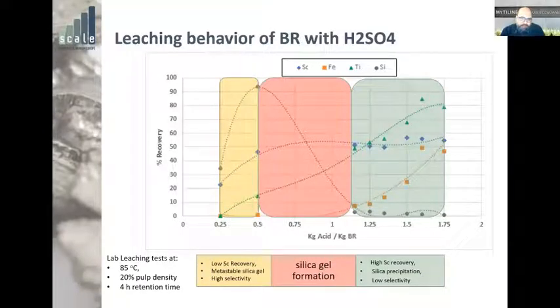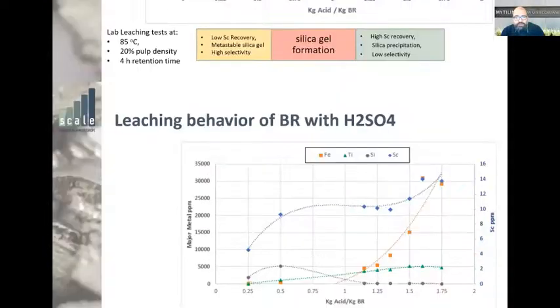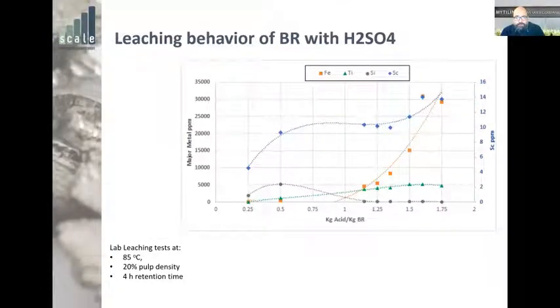And then there is this very narrow region in the beginning where we get relatively low scandium recovery. We get, however, high selectivity in terms of iron and titanium, and the solution does not form a silica gel, even though it has dissolved more than 100 ppm of silica, but it seems to be in a metastable state, which can last for many, many days and could be a viable window for operation. So we have now pinpointed two operational windows, the yellow and the green one, and we will start investigating these two. It's also important to understand a bit what kind of PLS we're producing in these regions.